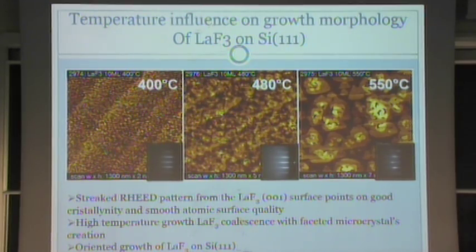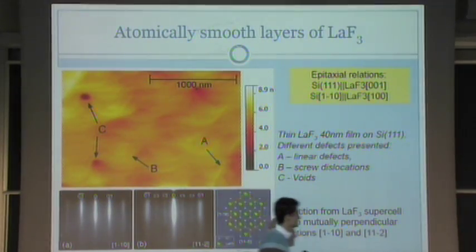samples grown at different temperatures, 400, 480, 550, and as you can see, small islands grow bigger, so they coalesce at higher temperature, and I want to point out moreover that through diffraction, it can be seen that we've got oriented growth. So it's not just a polycrystal on the surface. So they have got good crystal quality. And after series of preliminary growth, we were able to obtain really planar structure of lanthanum fluoride with, here you can see monoatomic steps of lanthanum fluoride.